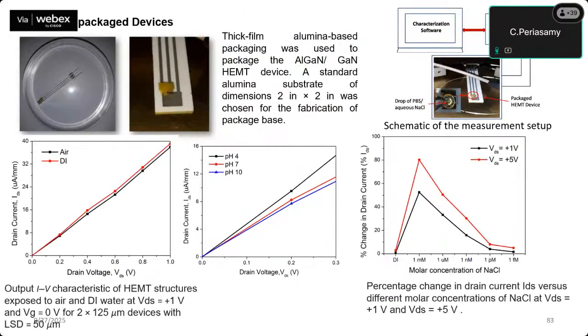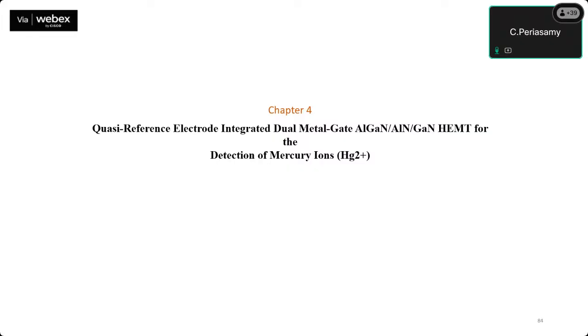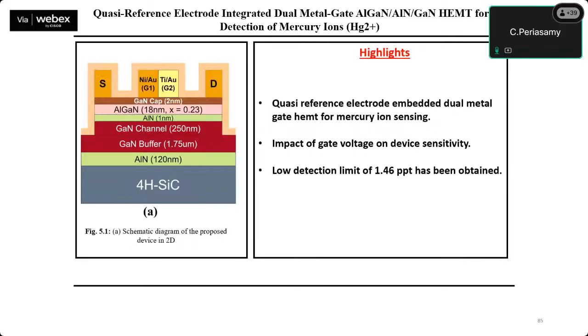Particularly we have tested pH as well as NaCl. Compared to pH, if you use this fabricated structure to detect NaCl, it is not giving better sensitivity. Similarly, this proposed HEMT structure we have simulated for heavy metal ion detection.